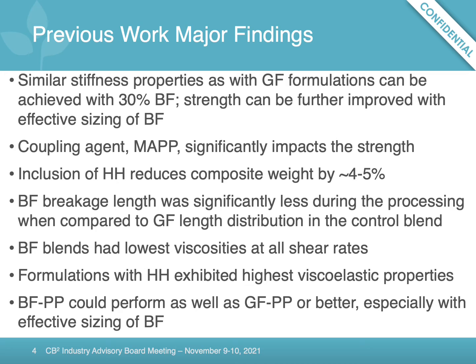Breakage of basalt fiber was significantly less than glass fiber breakage. And the basalt fiber blends generally yielded lower viscosities at all shear rates when processed. However, the formulations with hemp-hurd exhibited the highest viscoelastic properties. And so at the end, we found that basalt fiber polypropylene could perform as well as or better than glass fiber polypropylene, especially with effective sizing of basalt fiber.